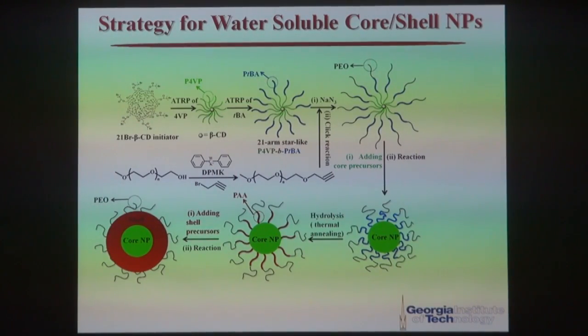So again, if you want to do a lot of biological study, you want this core-shell nanoparticle to be water-soluble. To do that, we simply replace the outer polystyrene block with polyethylene oxide. Once the outermost block is polyethylene oxide, you do the similar reaction with the core precursors first, getting the core nanoparticle, then do the hydrolysis, getting the intermediate block situated on the core nanoparticle converted into hydrophilic PAA, adding the shell precursor, and you get the core-shell nanoparticle, now permanently capped by water-soluble, biocompatible polyethylene oxide on the surface.